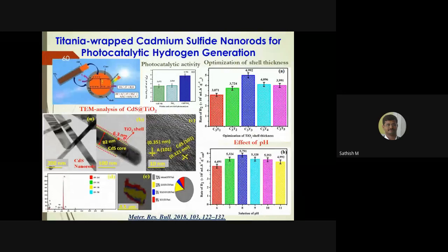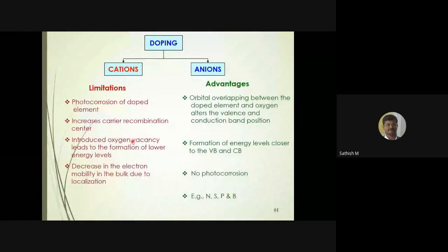Also, as I told you, the thickness of the TiO2 will be around 6 or 7 nanometers. The point is, if you put it more thick, the TiO2 will not allow the light to penetrate. At the same time, if you put it very thin, or it's not a uniform coating, then your cadmium sulfide will be exposed, and it will undergo decomposition.